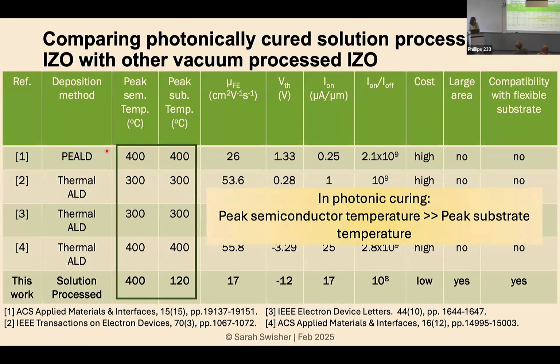So it's the same when you do ALD, right? Your substrate has to be able to withstand this 400-degree RTA that happens to convert the semiconductor and get it into the characteristics you want. Versus the solution processed method with photonic curing, our substrate only got to about 120 here. So we're really interested in this for back end of line applications as well. And so this is something that we're exploring.